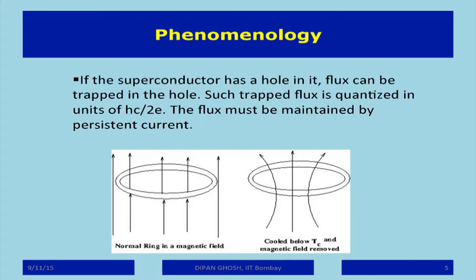Those which are closer to the inner edge of the sample will simply go to the hole. Now I do something else: I withdraw the magnetic field. If I withdraw the magnetic field, these flux lines have to go to infinity, right? The magnetic field vanishes, but there is no other way for them to go to infinity than to traverse through the material of the sample, and the ring being a superconductor is not going to allow that.